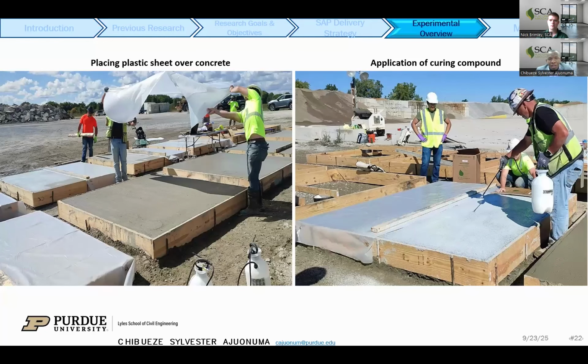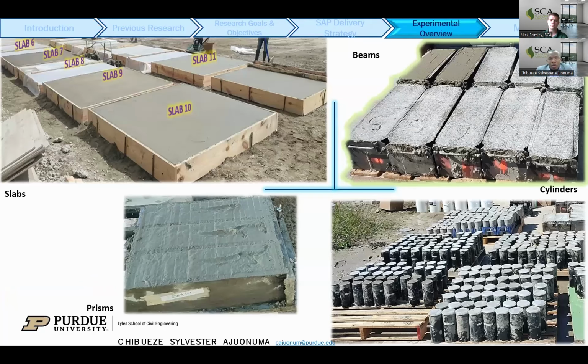I also want to emphasize for curing, the slab was partitioned, and half of it was covered with plastic sheets, whereas on the other half we applied the curing compound. And so this is an overview of all the slabs after we finished the work. Beside the slabs that we made in the field, we also cast 6-inch by 6-inch by 18-inch beams for flexural testing, and prismatic specimens, as well as close to 200 cylinders for compression testing.